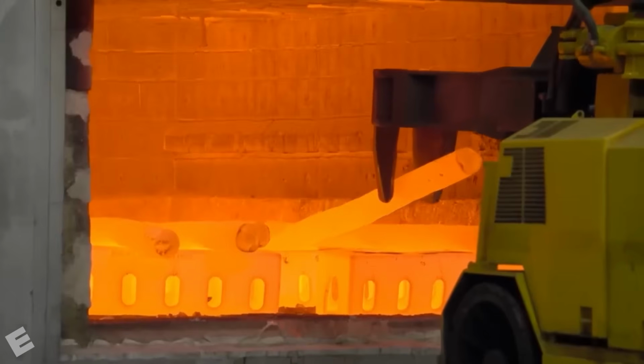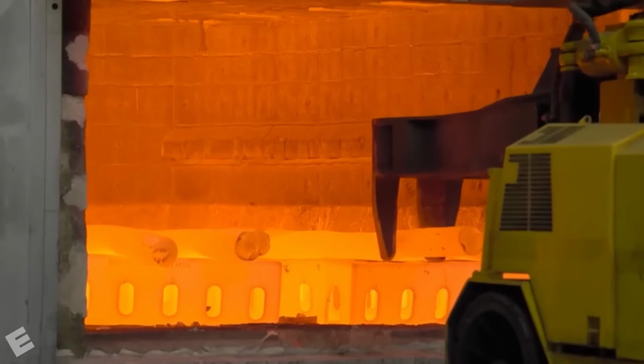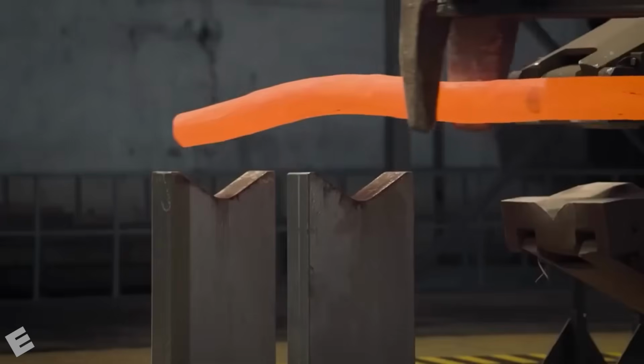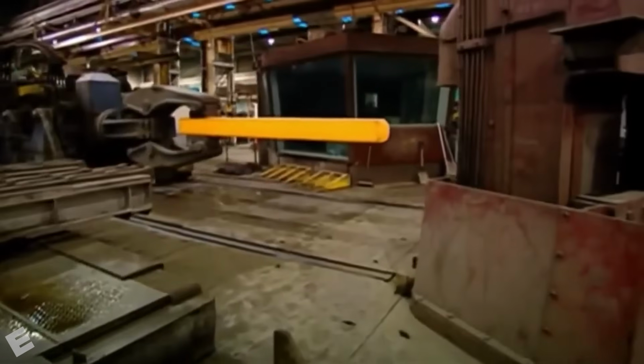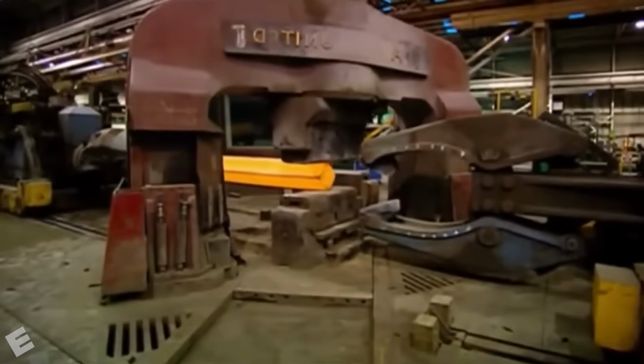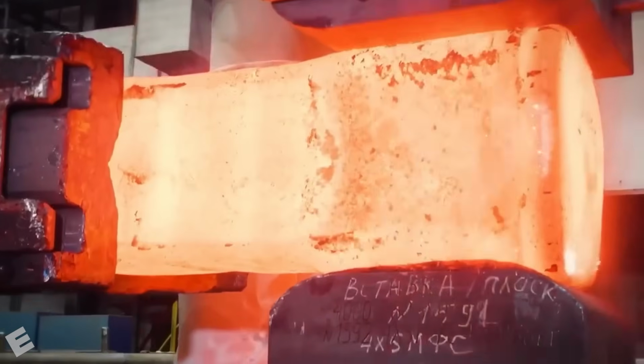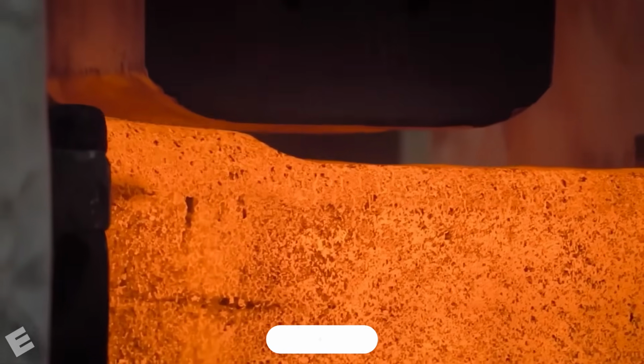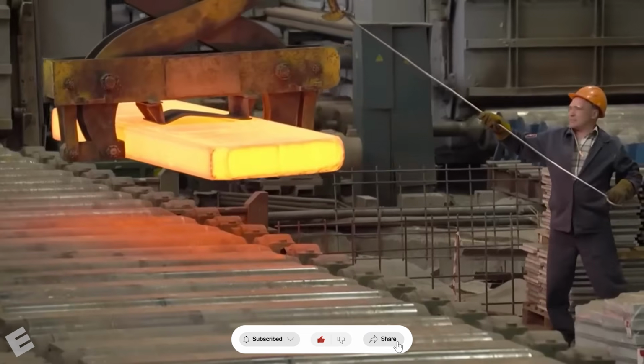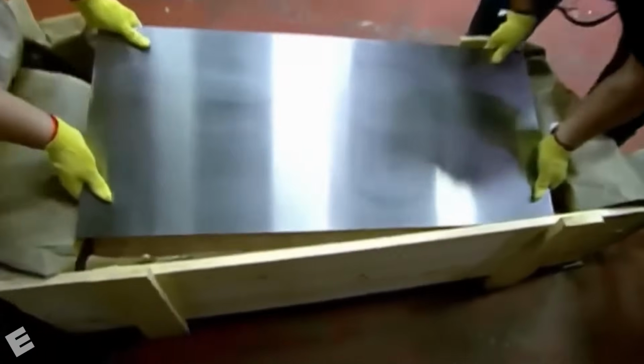Before titanium can be forged, it must first be softened with heat. The ingots are placed inside industrial furnaces and heated to temperatures approaching 2,000 degrees Fahrenheit. At these temperatures, titanium becomes sufficiently malleable to be reshaped without cracking or breaking. When the metal reaches the correct temperature, enormous robotic clamps remove the glowing ingots from the furnace and carry them to the next processing station. There, colossal hydraulic presses capable of applying thousands of tons of pressure begin forcing the metal into new shapes. Under this tremendous force, the ingot slowly deforms. It may be reheated and pressed repeatedly over several hours.